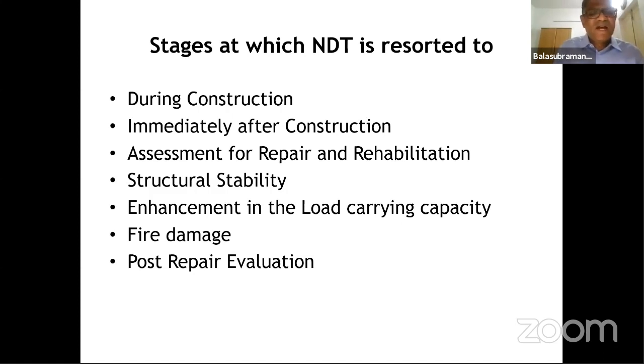Fire damage, generally fire damaged concrete tends to carbonate. Fire damage is mostly insurance-based investigation, so you have to be very careful. When you do a fire damage investigation, you have to test in the fire damage locations as well as in the non-fire damage locations, because the insurance people will ask you whether these defects were pre-existing. It is like our medical insurance. Were they pre-existing or did the damage happen only because of the fire? So you have to do it in the fire affected location, not so affected location, and completely unaffected location, so that the insurance guys are very sure about it. And then the post-repair evaluation. So these are the stages at which NDT is resorted to.